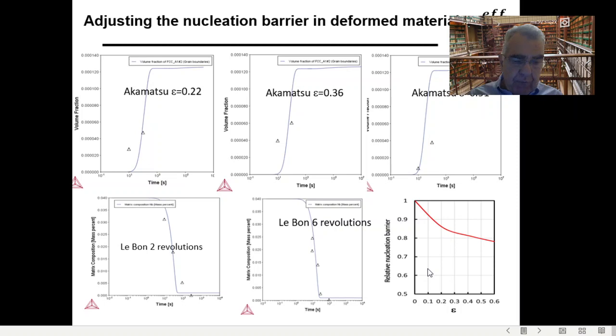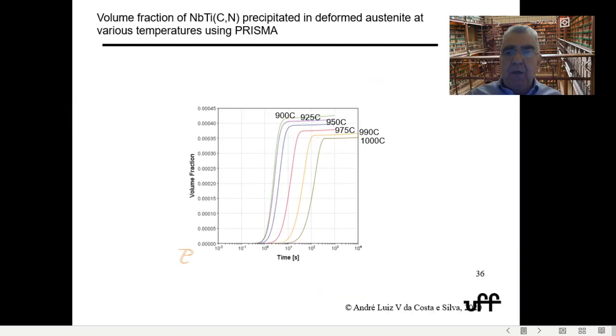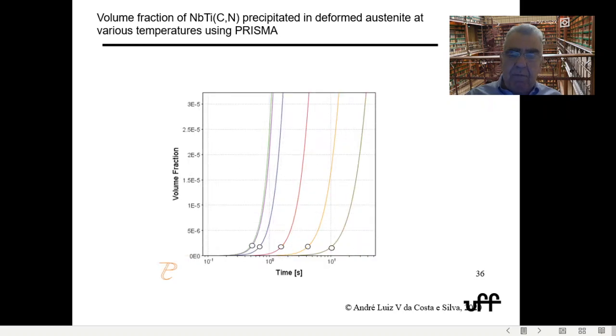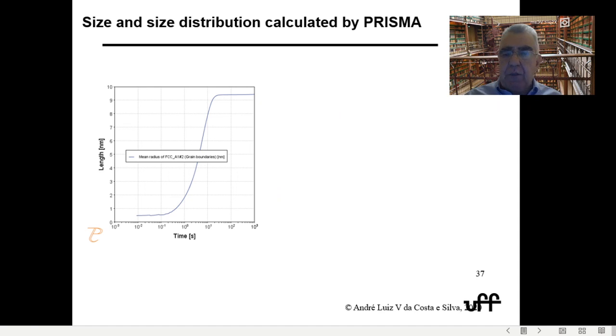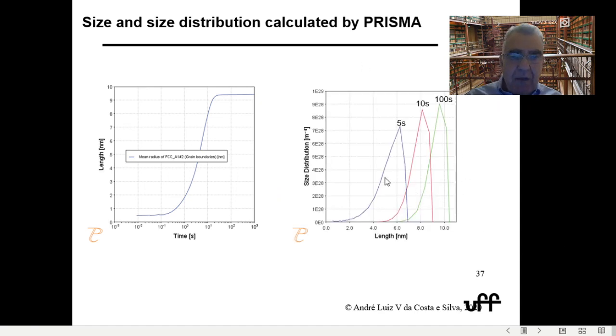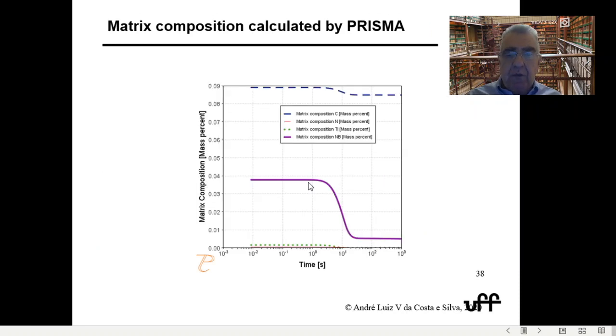So this now is fed back on the model, and we can do a volume fraction versus time precipitation for niobium carbide in a given steel. And if we want, we can take the 5 seconds, and then we can do this in different scales. We can see the size of the precipitates as it moves along the time. And this is very interesting because we can also calculate how, for instance, the niobium in the solution is going to vary as time goes by and precipitation happens. So you have a lot of information that you can try to use to better understand your recrystallization.